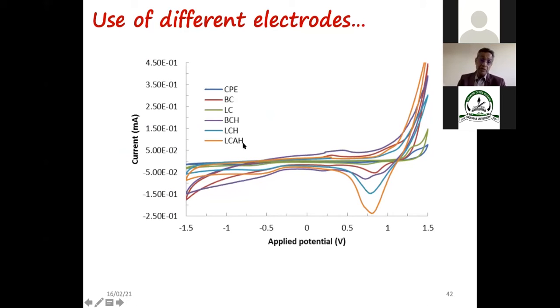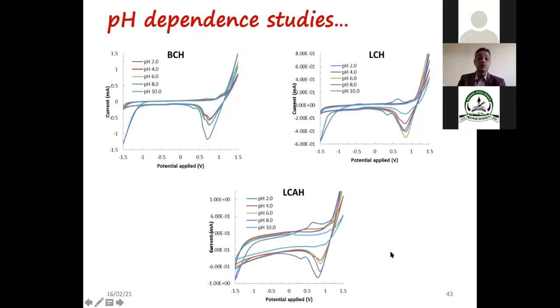These are the different materials: the bentonite, the clay, the simple carbon paste electrode. Then the carbon paste electrode is modified with pristine bentonite, pristine local clay, and then the organically modified hybrid material for the bentonite and for the local clay, and then the local clay pillared with aluminum and again organically modified. This modified clay material gives very high signals. Then we did the other studies, the pH studies, using the different modified materials.